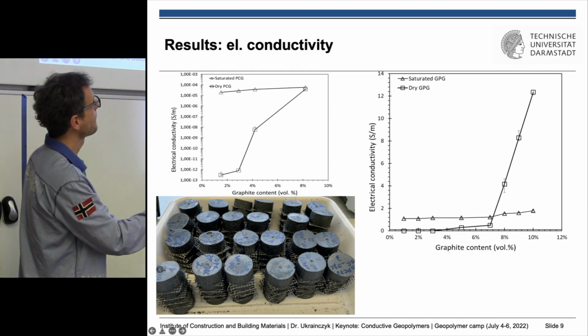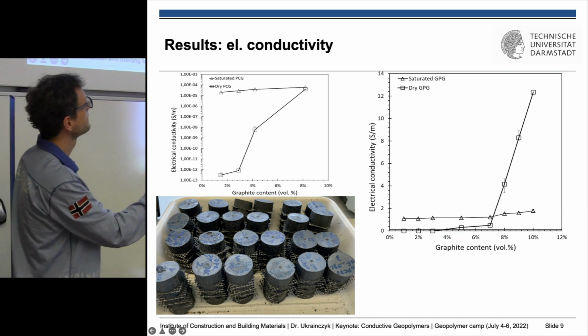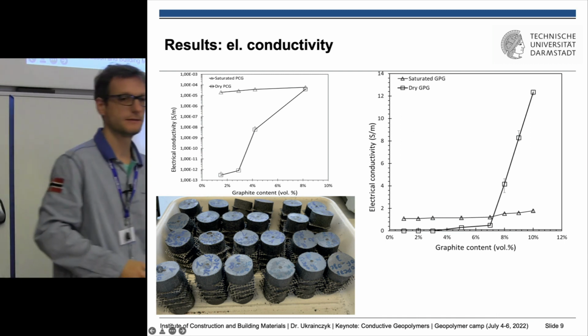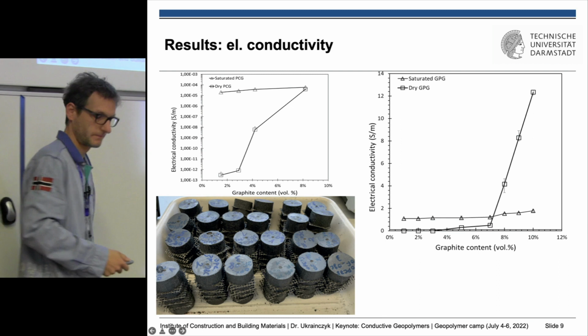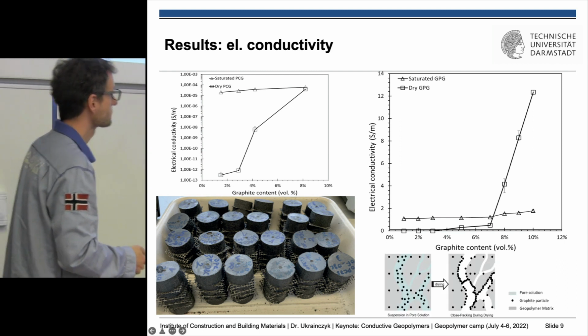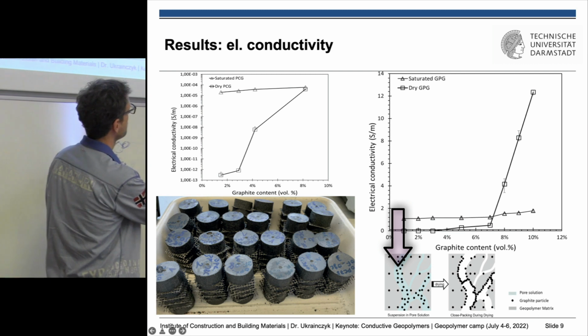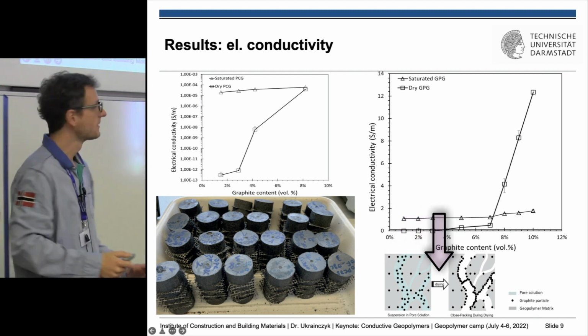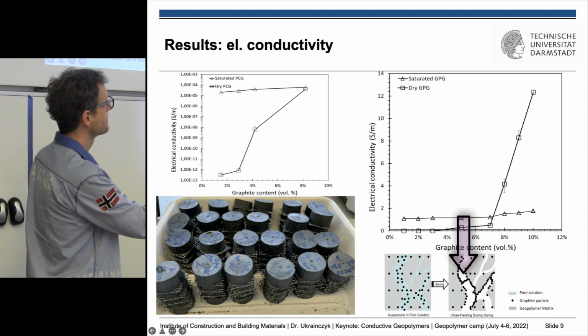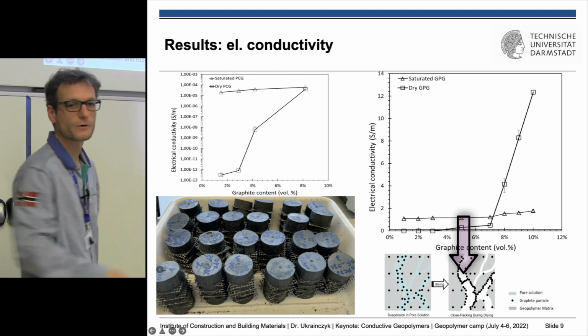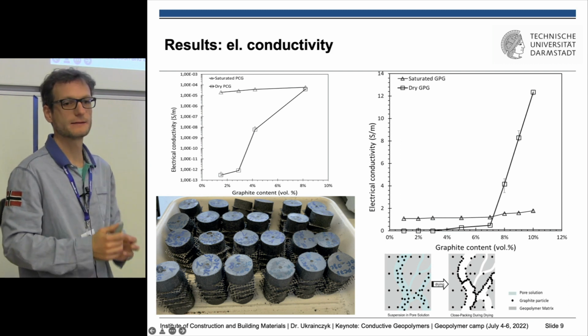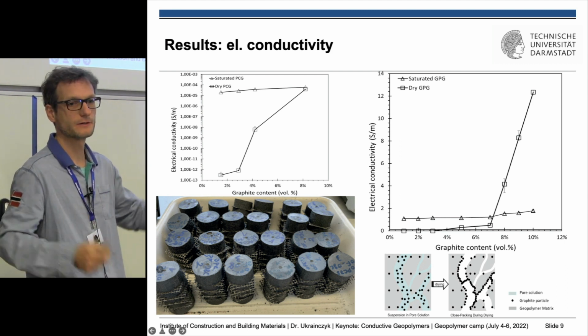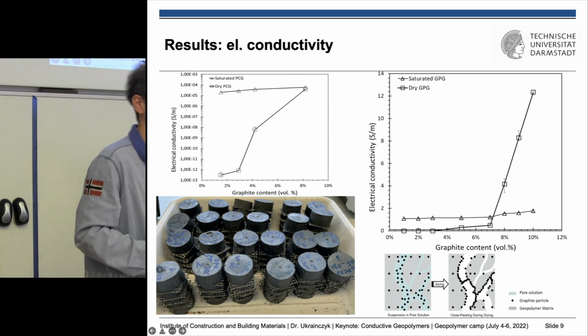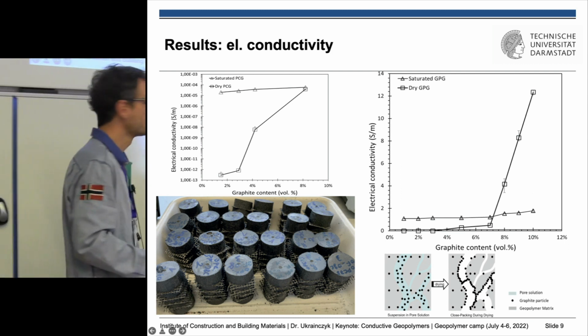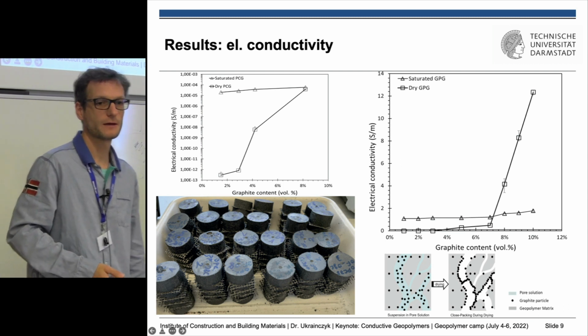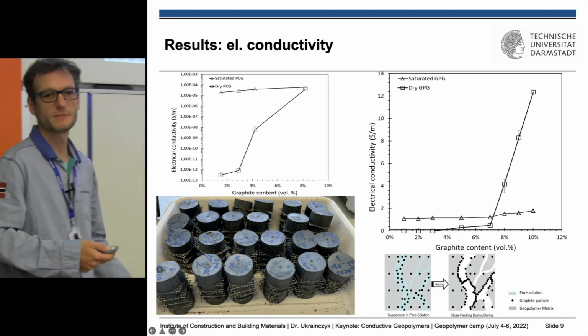Those are the values. But interestingly, when we dried the material, we got even higher increase in the electrical conductivity, which we explained by this sketch. Because the graphite particles are in the porosity, but when we dry it, they start to form more of this percolated, connected network of the graphite particles. So here the porosity is really a key to tune, to tailor this kind of applications.